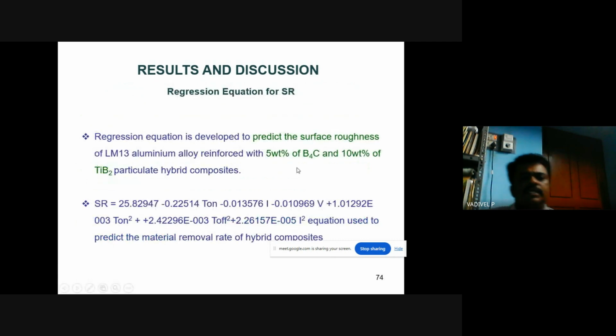So here the regression equation is developed. The regression equation for the surface roughness is developed to predict the surface roughness. Surface roughness means how smooth or how rough the surface is. The aluminum 13 alloy reinforced with 5 weight percentage of boron carbide and 10 weight percentage of titanium diboride particulate hybrid composite has the predicted surface roughness. The surface roughness equation is used to predict the results of the hybrid composites.